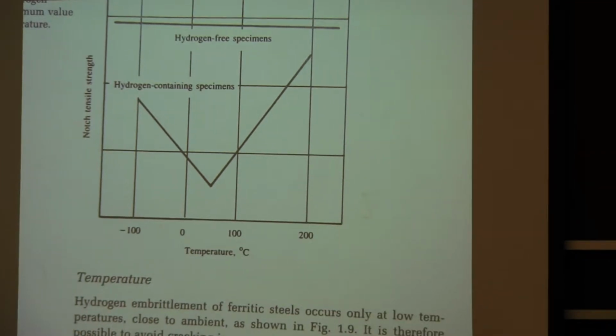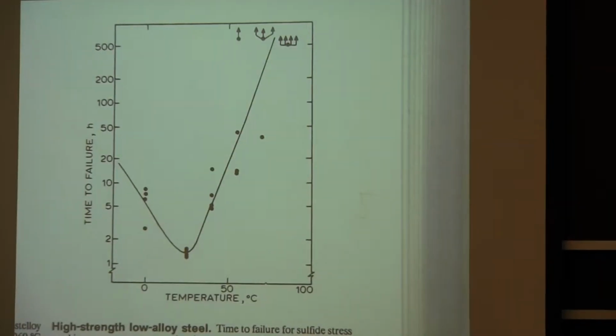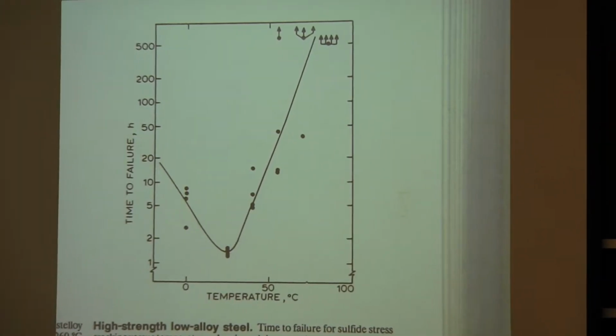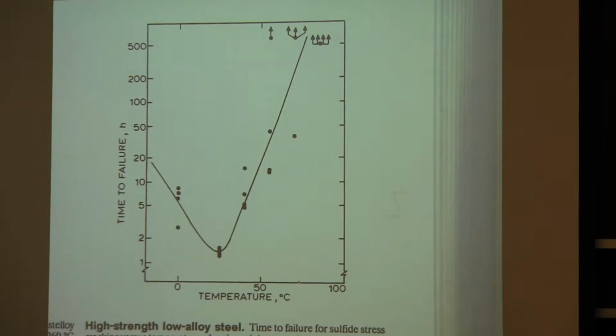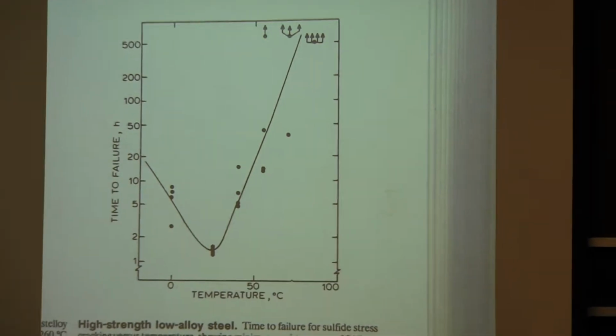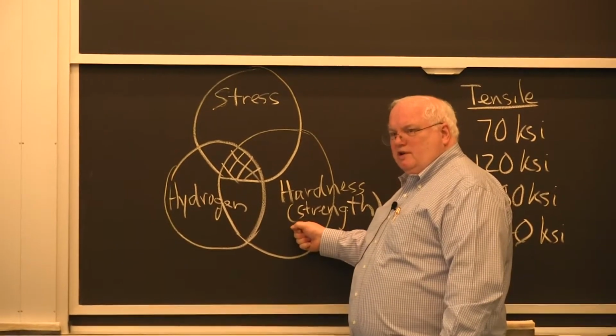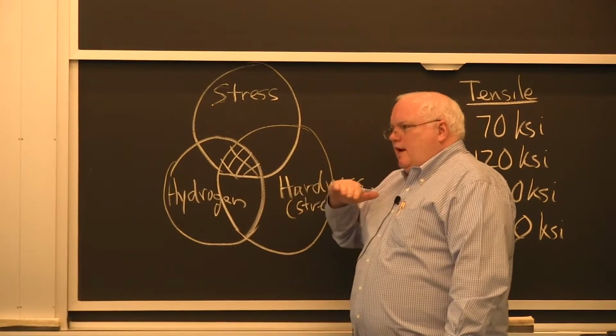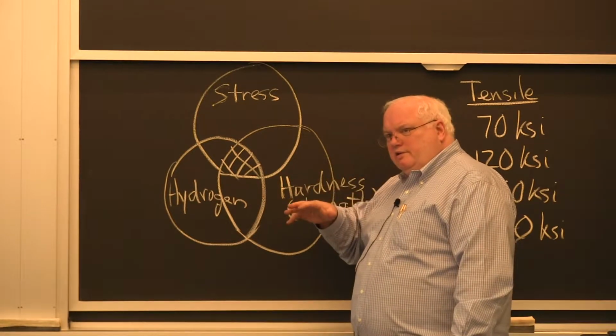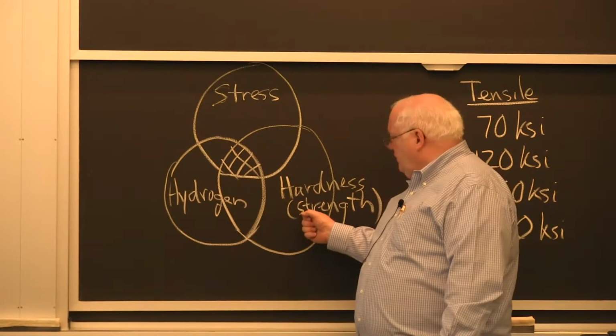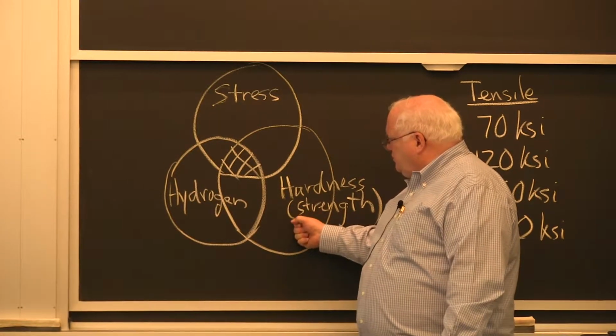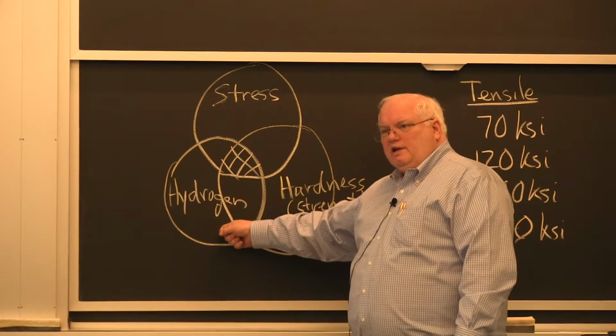This is just a schematic. I do have a plot that actually gives you hard data. This is not from welding. It's from hydrogen sulfide stress corrosion cracking. Yesterday, one of you asked the question about what's stress corrosion cracking, and I got up here and said, well, it's the same Venn diagram. Stress, a susceptible microstructure. In our case, it's the strength of the steel, but for stress corrosion cracking, do you have carbides along the grain boundaries of the stainless steel that it can etch and eat away because of the difference in composition? And do you have chlorides that are going to eat that away?